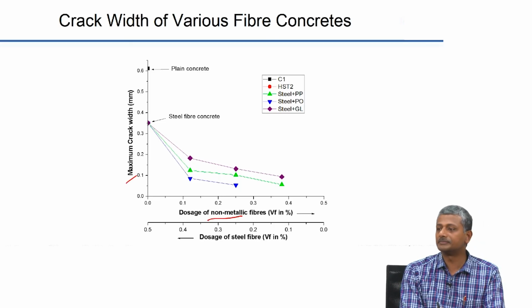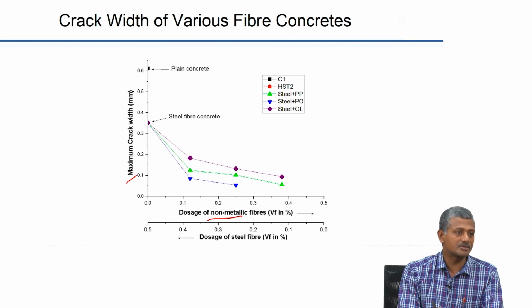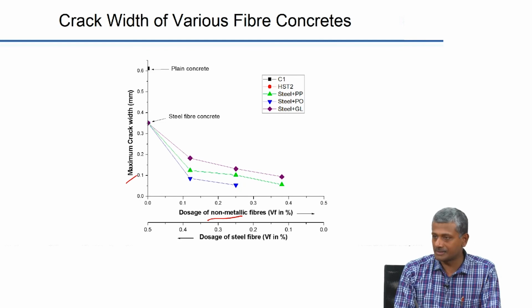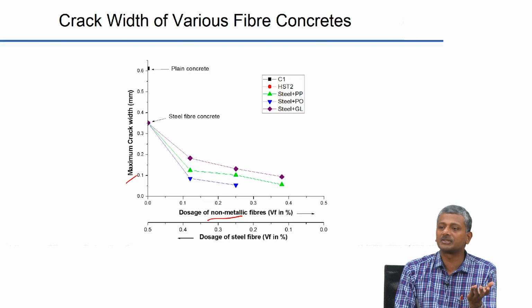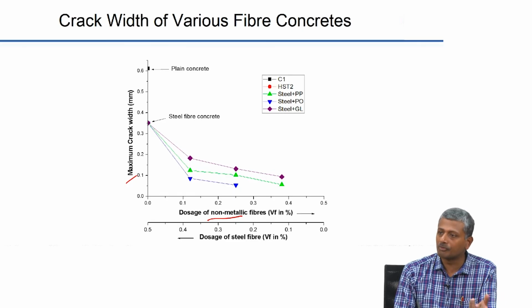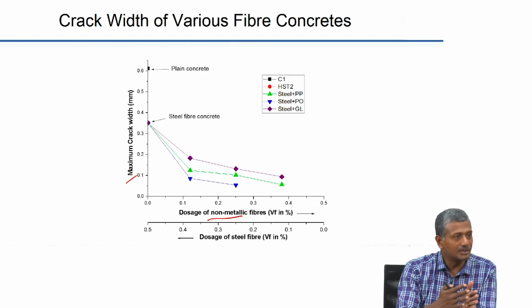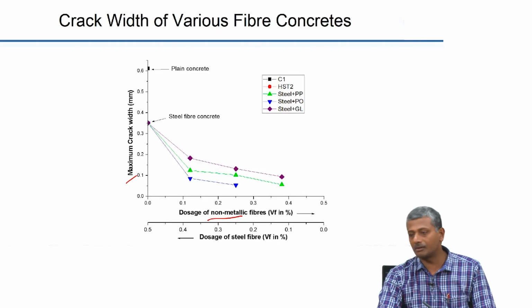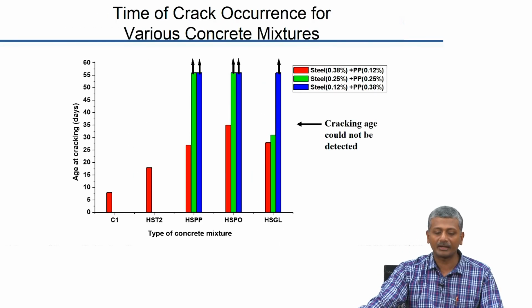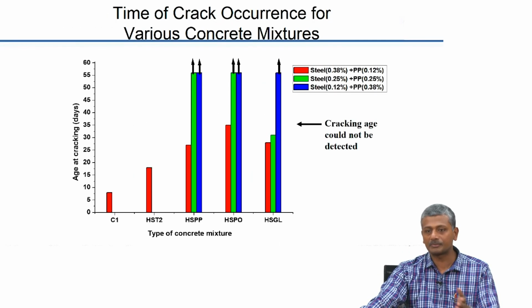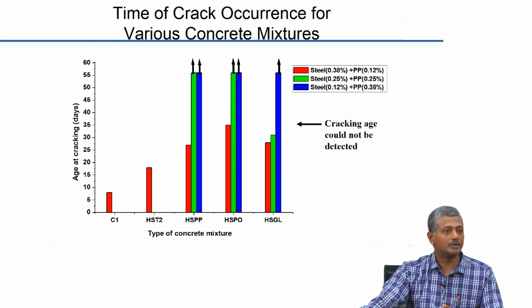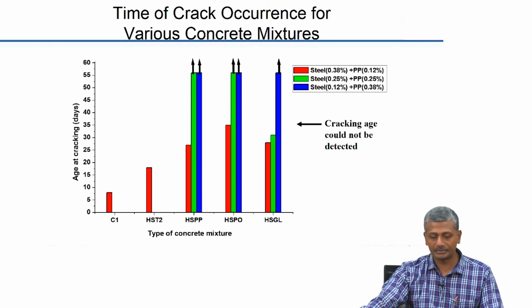As you increase the extent of non-metallic fiber in the system, your maximum crack width is getting lesser, because you have more number of fibers bridging the crack, right. Glass, polyester, polypropylene, these are lower density as compared to the steel. So, for a given mass of the fiber, there will be a lot more fibers which are actually present, and these will be bridging the crack. That is why the overall crack width is going to get reduced in the system. And again, time to occurrence of cracking increases as you substitute the steel fibers with the non-metallic fibers. Okay, thank you.